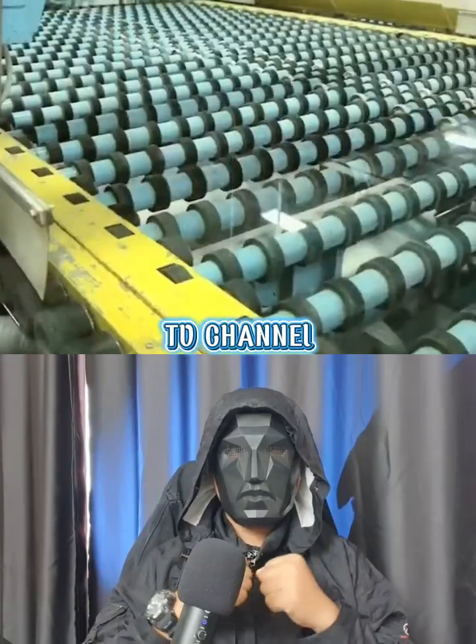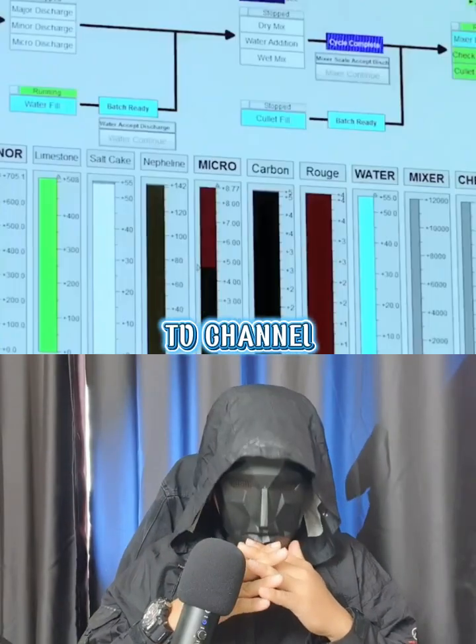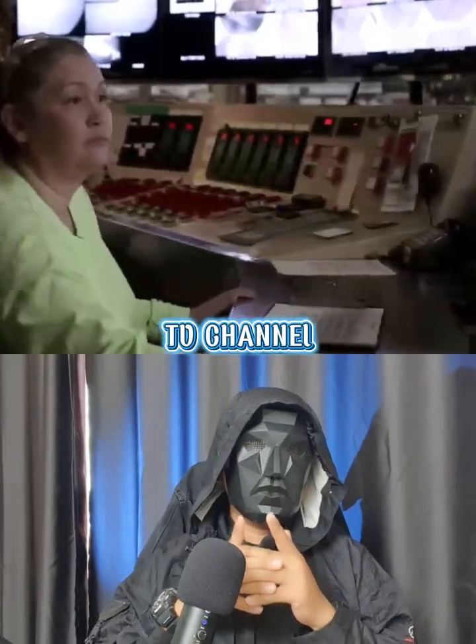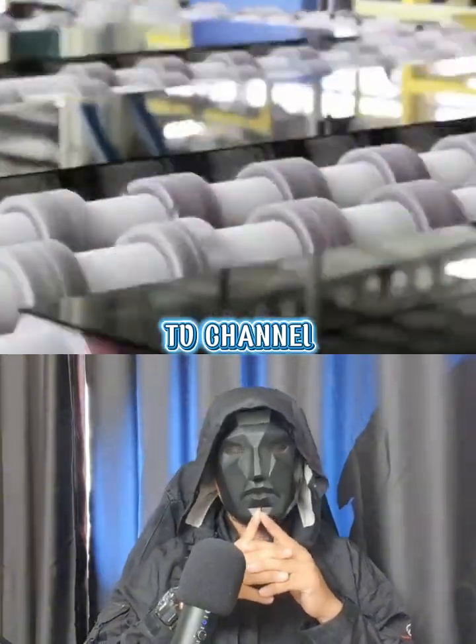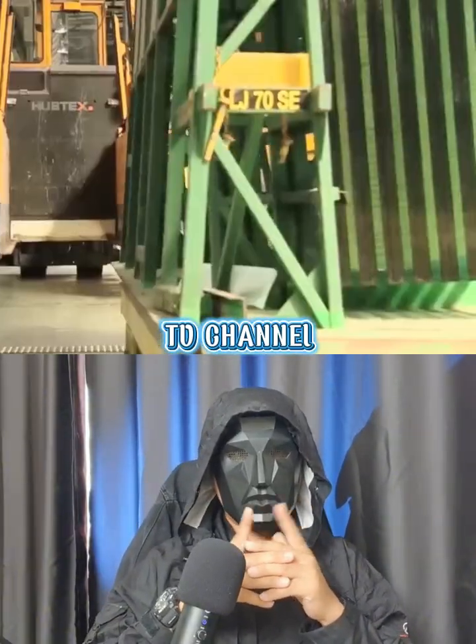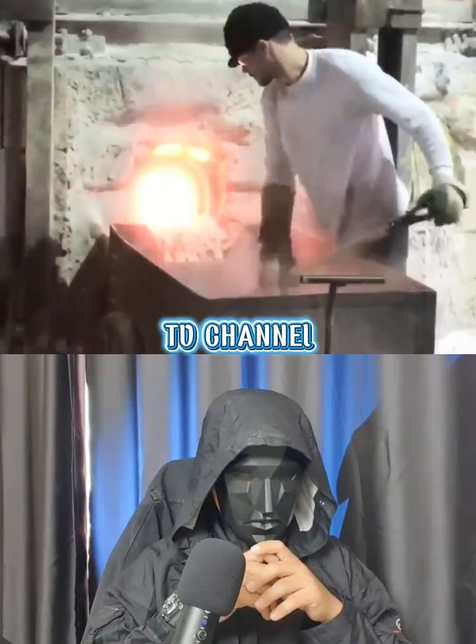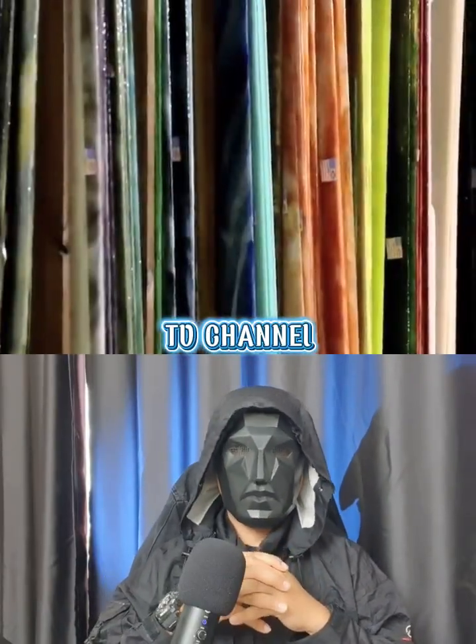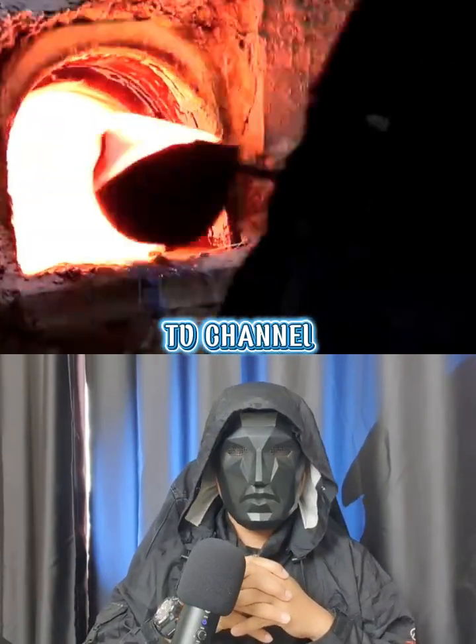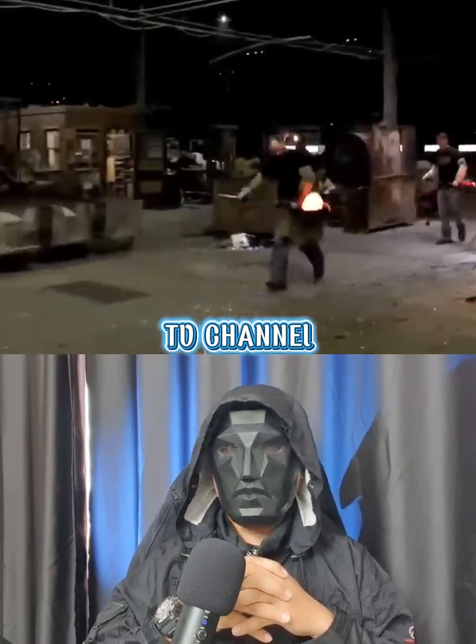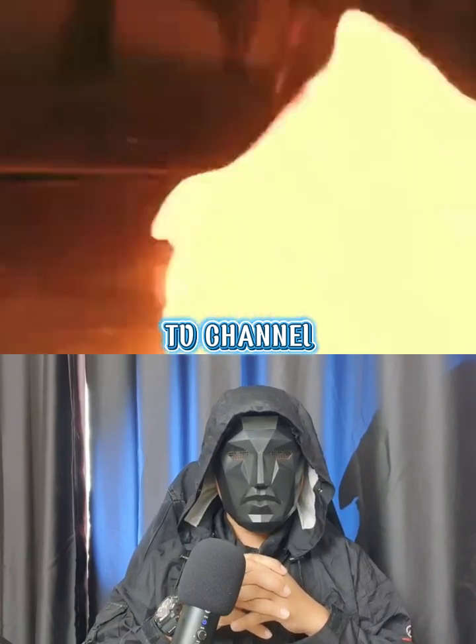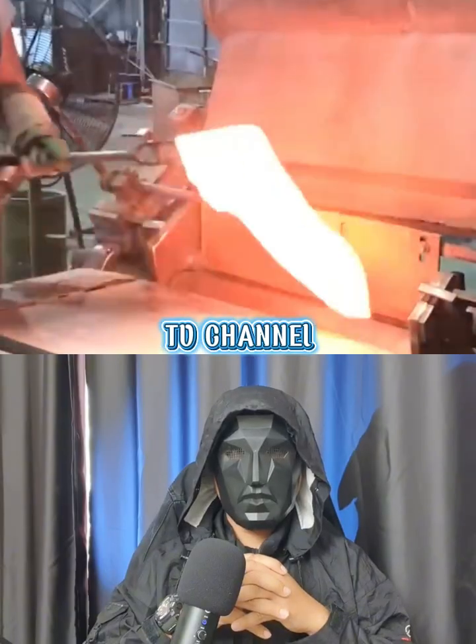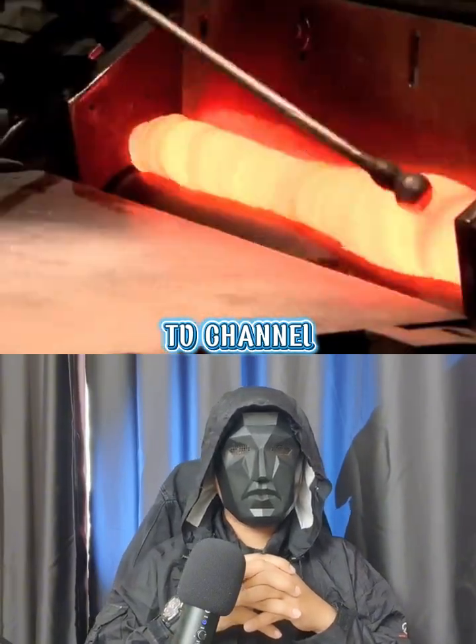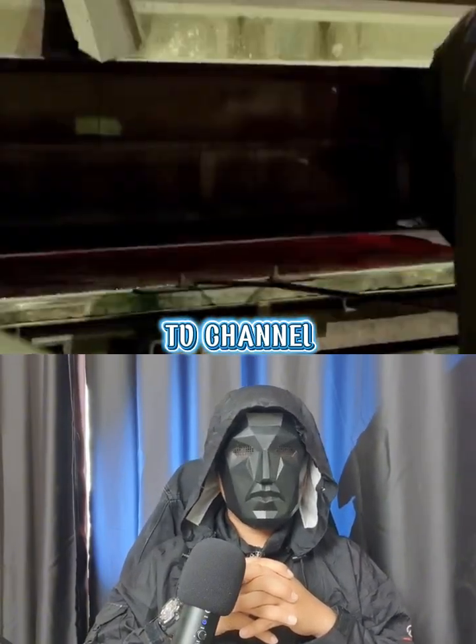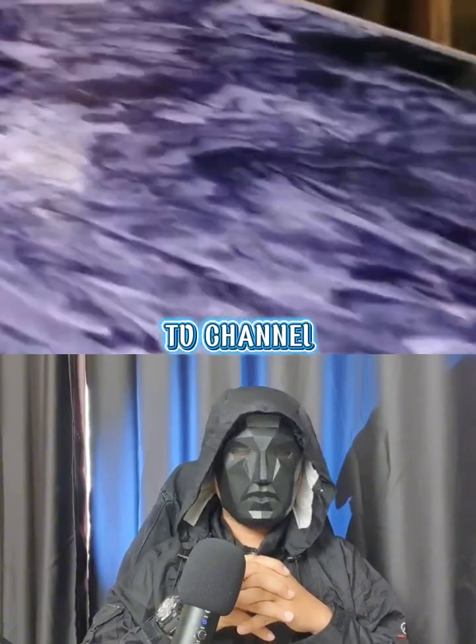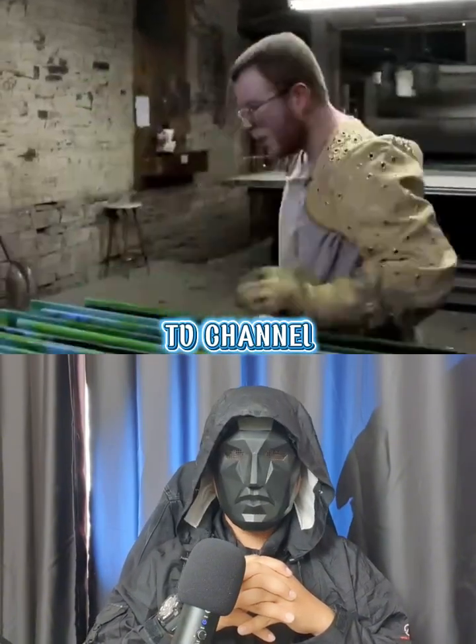The molten glass at about 1100 degrees Celsius flows gently from the furnace onto a large bed of molten tin. The glass, which is less dense than the tin and immiscible with it, floats on the surface, similar to oil on water. This creates a perfectly level, mirror-like surface on the bottom of the glass ribbon, which is known as a fire finish. The thickness of the glass ribbon can be precisely controlled by adjusting the speed of the line and using top rollers, knurls, to stretch or compress the ribbon.